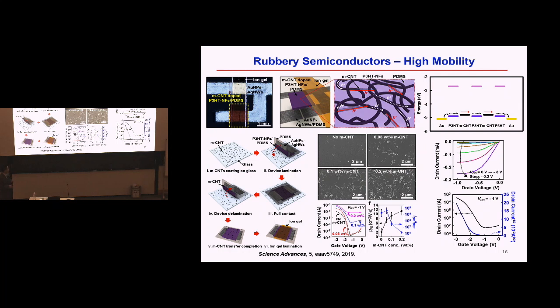So here, the optimum is that we utilize 0.05 weight% of metallic carbon nanotube. We can achieve a mobility of 10. So basically, you're boosting from 1 to 10.